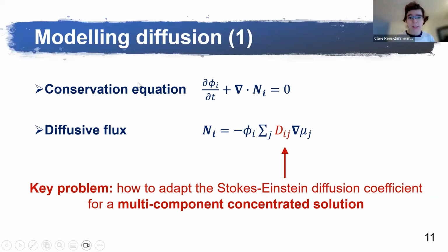So I've written down a conservation equation for the volume fraction phi of each component i, where i would be 1 or 2 in a mixture of 2 different particle sizes in solvent. The diffusive flux N for each component is found by summing over the Fick's law contributions from each component in the mixture. A key problem was that the Stokes-Einstein diffusion coefficient was originally derived for a single particle diffusing in infinite solvent. But here we have a multi-component concentrated solution.